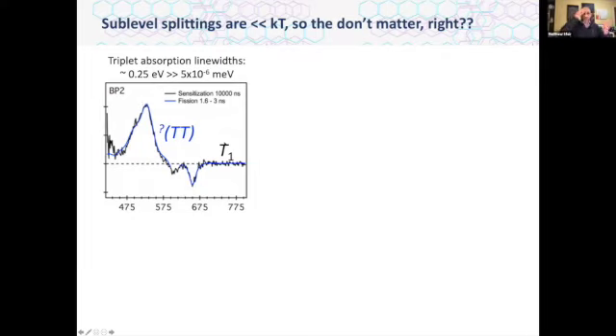We can do experiments where we put one triplet on a pentacene or two triplets on a pentacene, and we can look at differences in the line shape for the triplet absorption. And you can see we have line widths on the order of 250 millielectronvolts, way greater than, again, what we said our sublevel splitting was. And even more concerning, there's no difference between one triplet and two triplets in terms of the spectra we get. So again, you would think those splittings are so small they can't do anything, or again, there's no way to see that using purely optical means.